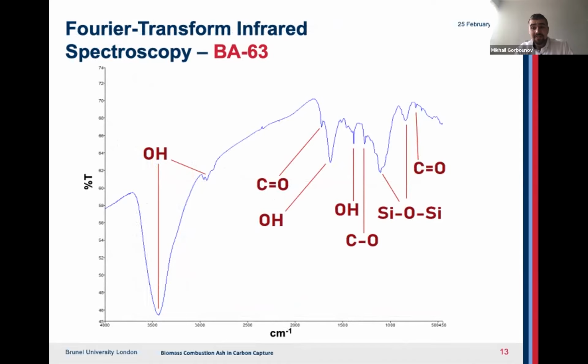The FTIR spectrum of BA63 is presented on this slide, and as the two investigated materials are both BCAs coming from the exact same source, it is expected of them to have a somewhat similar composition. More than half of the peaks identified from both of the samples are either appearing at the same bands or close enough to be associated with the exact same chemical functionality. The two outermost peaks and another two in the middle were ascribed to the stretching and bending vibrations of the OH bond, and the band appearing at 1722 reciprocal centimeters was, just as with the fly ash, ascribed to the C=O bond. However, here is where the similarities end, as the wave numbers associated with the asymmetric and symmetric, respectively, vibrations of the Si-O present themselves at approximately 1100 and 840 reciprocal centimeters.